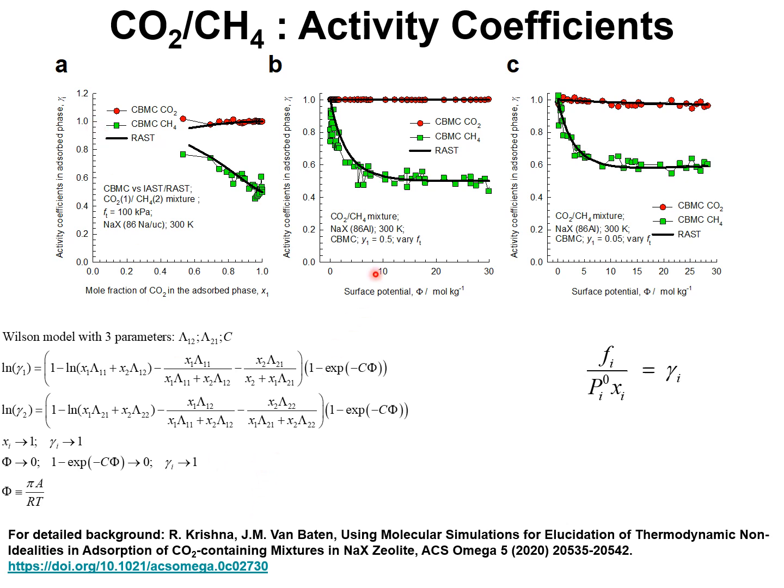If you look at the other sets of CBMC simulations in which the mixture composition in the bulk fluid phase is held constant and the surface potential is increased, we note that the activity coefficients of each of the gas molecules tend to unity as the surface potential tends to 0.